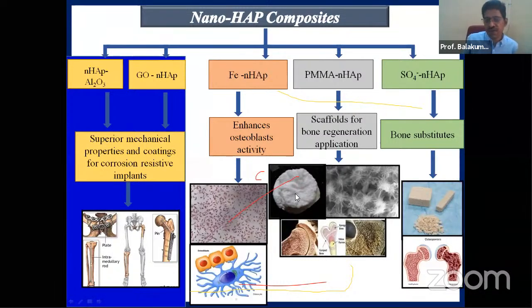There's another one, but when you form a material for scaffold, what we have done is the scaffold can be biodegradable, and it can be of a spongy nature because you cannot exactly fit where you have a bone defect. So spongy kind of thing, you can squeeze and fit it inside. So it has to be mixed with the polymer. Where you can use a PMMA or PLGA or PCL, and then we combine with the nano hair, we are able to make a porous scaffold. And then now we move from this freeze drying method to a 3D method; there are many techniques that we are using. Similarly with sulfate, which we have made, and also that kind for bone substitution.